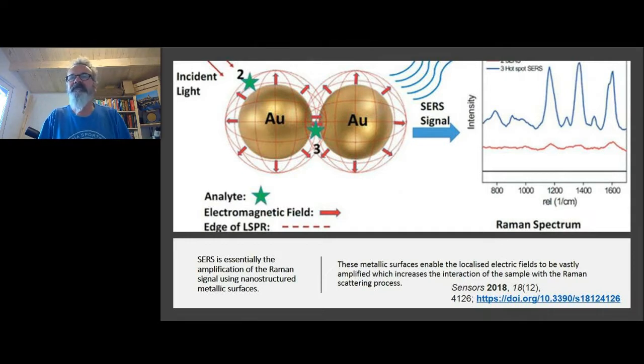I won't go into this in detail, but essentially, if I can make a nanostructured surface, a nanostructured metallic surface, it acts as a nano aerial and it interacts with the light and the light scattering, and we have the potential to amplify what is an inefficient Raman process. In a normal Raman process, one photon in a million has the right kind of scattering event that we can measure. By using nanostructured metallic surfaces, we can amplify that signal by up to 1 million times 1 million times, so about 10 to the 12 times. If you can amplify at that kind of scale, that gives you the opportunity to do extremely sensitive measurements.